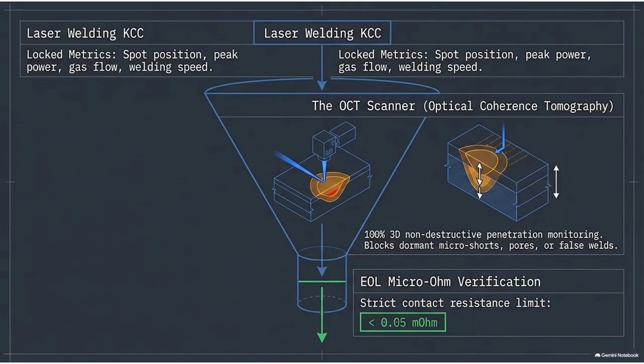In the battery factory, this OCT scanner is mounted directly adjacent to the laser head. As the laser is violently melting the metal, the OCT is looking straight into the molten pool, performing 100% real-time, non-destructive penetration depth monitoring. Wow. It verifies that the weld physically penetrated deeply enough into the bus bar, and it can actively see if there are any microscopic gas bubbles trapped inside the solidifying metal. So it's performing a 3D medical ultrasound on every single weld as it happens.